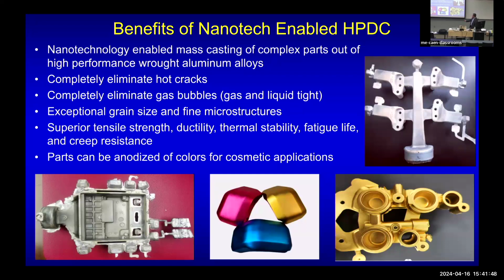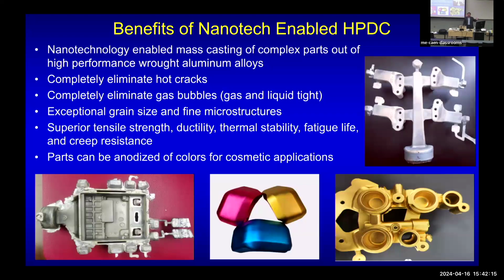But anyway, we're also working with the big companies, right? Especially in the cosmetic consumer electronics domain, right? So we found we need colors. I need all these different colors to match all these industrial products. And this is all by anodizing. Traditional casting alloy cannot do that because you have too much silicon. They will not get the color out. But right now we use a low-cost alloy, you don't have the silicon there to block you. You can make all the colors. So this is one of the biggest, fast growth areas for our application.